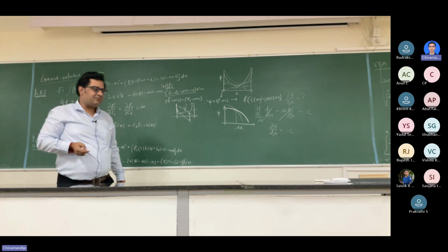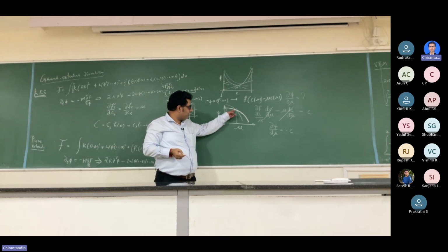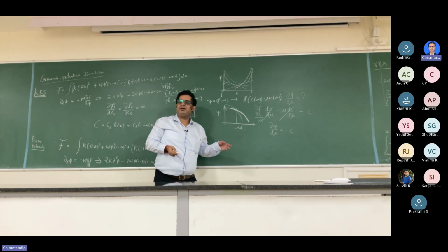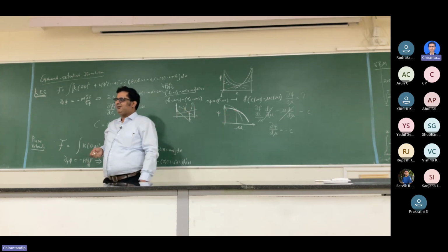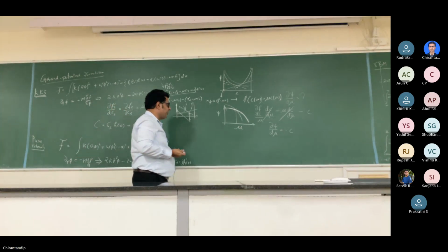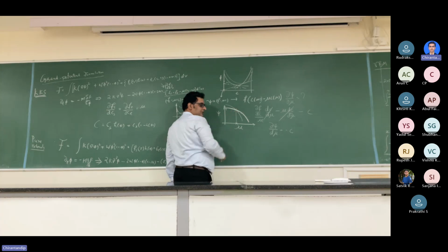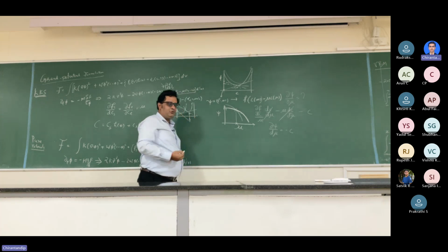No, I mean, what does this intersection point represent? This is obviously the effective chemical potential. What does this intersection and equality of psi thermodynamically represent? That's essentially the common tangent. Right? Why? Because the psi are equal and it is at that mu that the intersection happens. The psi are equal and therefore that is the common tangent. Right? So what did you do over here?